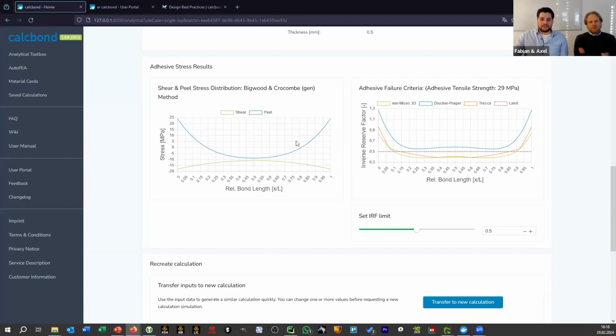And also we have peel stresses induced by moments as a result of the asymmetrical load introduction and the thickness offset of the joints. These stress components are calculated inside the adhesive layer and then transferred into a failure criterion, which we see here in the box on the right. This basically predicts the cohesive failure of the adhesive layer itself.